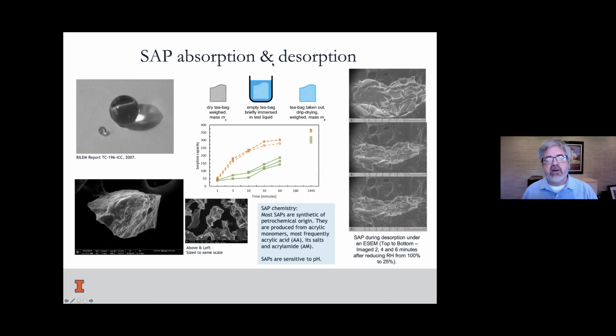We have an absorption behavior and a desorption behavior. If you wanted to test this, you might put a sample of the superabsorbent polymer in a tea bag, literally a tea bag like you make tea with, with a paper around it to keep it isolated. And then as water is absorbed, the weight of the bag of saturated particles becomes heavy. We measure that. And then later on, we can see it desorb as there's some kind of a demand for that water outside. So in this case, we just saw a couple of different samples of brands of SAP. And the simple point is not all SAPs are the same. Some absorb more, some absorb more quickly. And so we would not want to make the mistake of saying they're all the same.